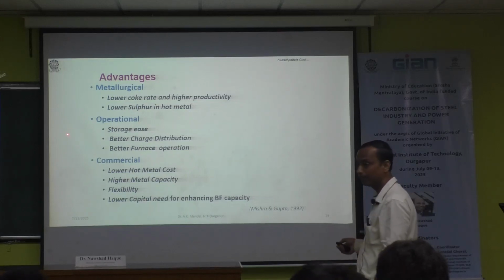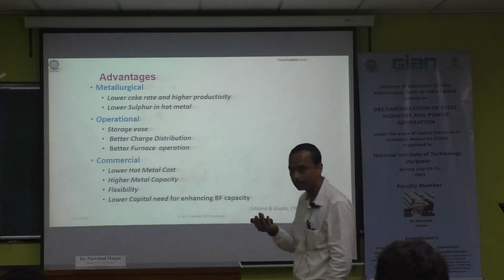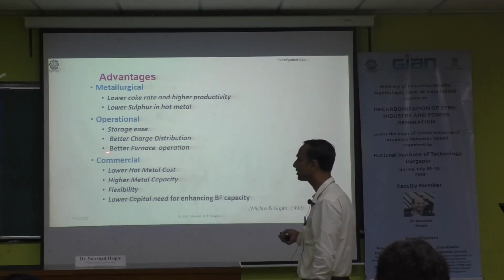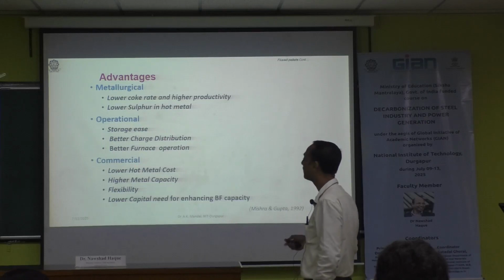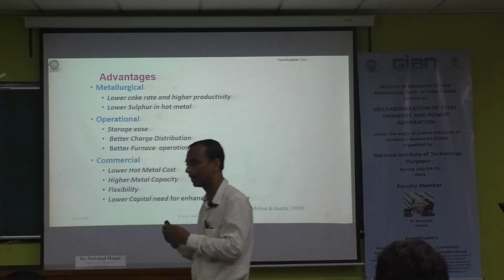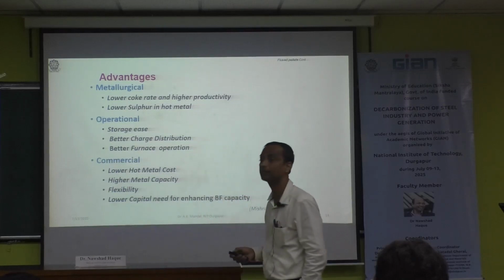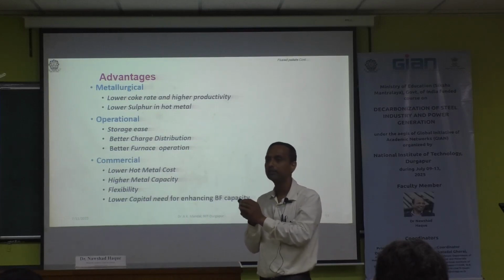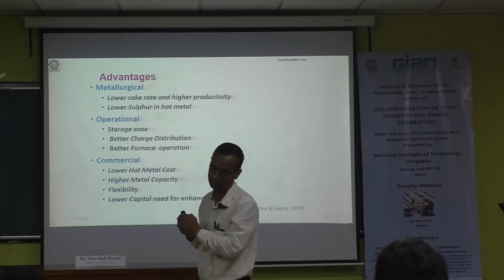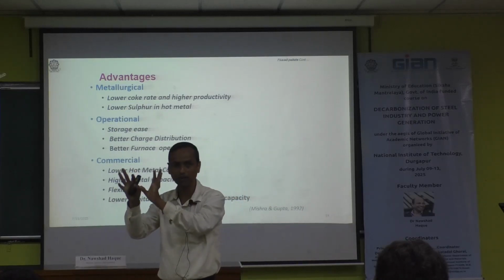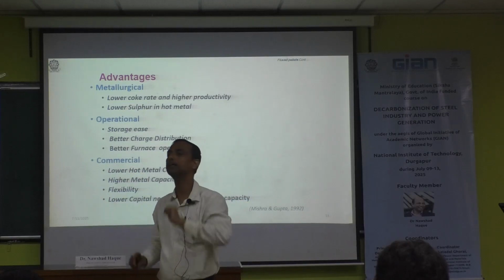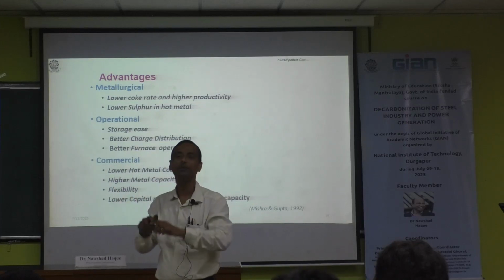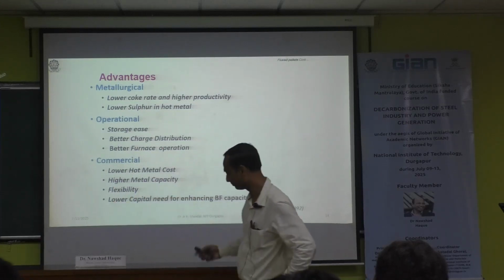And the operational benefit is that storage is easy. In storage, you will not have parabolic nature, therefore you can store easily. Better charge distribution, size is typically more. Better furnace operation as the interparticle space is high, and permeability is high. Your sphere will give you the maximum value. Many shapes, on changing the orientation, the permeability of the bed will differ. Triangle low, square low, point is high. Only the sphere, if you change the orientation also, the bed permeability is not altered.